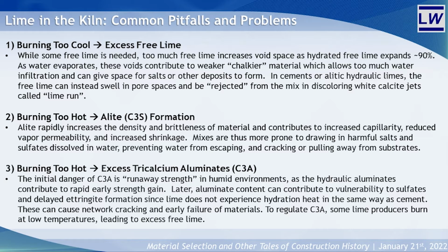Alite, which forms tight needle-like networks, increases the capillarity of the material, while driving up its density and down its vapor permeability. So while it takes longer to get wet, when it does get wet, the water and any dissolved materials in it are drawn deeper into the material, where they are held on to much longer, contributing to deterioration from a variety of sources, most commonly salt crystallization, freeze-thaw damage, and gypsum incrustation.